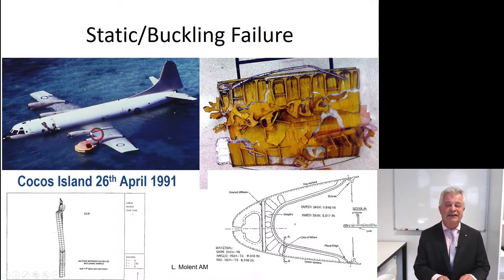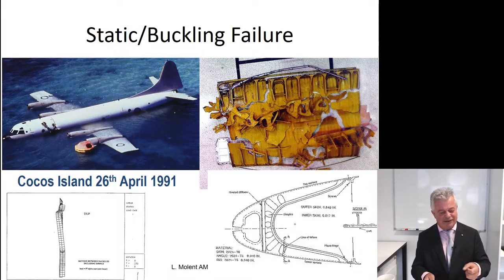Long story short, we recovered the leading edges. Here's one leading edge, a section between the two engine cells, and that's what it looks like. It immediately became clear that the ribs that gave it the shape, there's a rib, failed at the identical point along the span of that leading edge. Wow, that's a clue. So the investigation was, why did this happen? The other issue I can tell you is that we can determine that the airplane really didn't sustain a high sustained maneuver load that would explain why the leading edges may have popped off. Long story short, the first discovery was that at the speed the aircraft was doing and at the G-forces that the pilot exposed the airplane to, the airplane was experiencing about Mach 0.53, pretty good for a transport airplane.